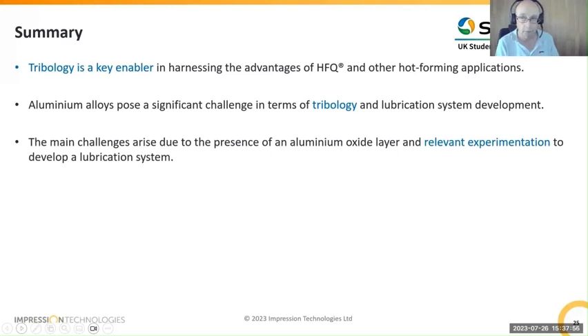And just to cover that a little more, one of the main issues with the typical tribology test equipment that is out there is that you pretty much have to run the tool material and the blank material at the same temperature, which isn't what happens in the industrial process. So that means you have to run multiple tests at multiple temperatures and also pressures and speeds in order to try and get an overall map of what is going on in terms of coefficient of friction and other lubrication regimes that are taking place.